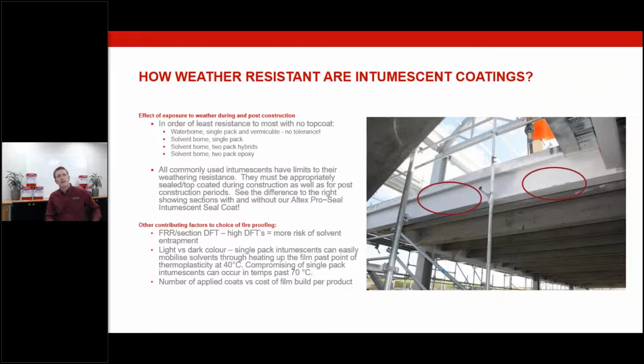The other common question that we get is how weather resistant are intumescent coatings or the coating systems? Most commonly, the actual coatings themselves. You've got the effect of exposure to weather during as well as post-construction, and they can have two different impacts. In order from least resistance to most resistance to weathering with no top coat, you've got waterborne materials, which are single pack obviously, and vermiculite fireproofing products. They've got virtually no tolerance. They may look fine, but the intumescent properties of those coatings, particularly if they've been exposed to constant weather, particularly pooling and ponding or very high humidity, will be very much compromised or even dead.